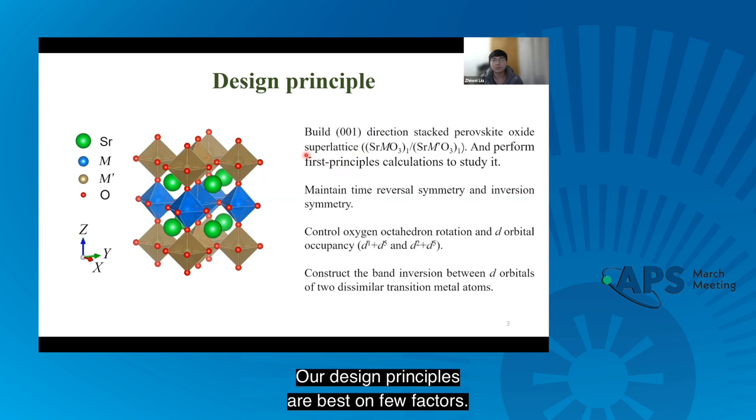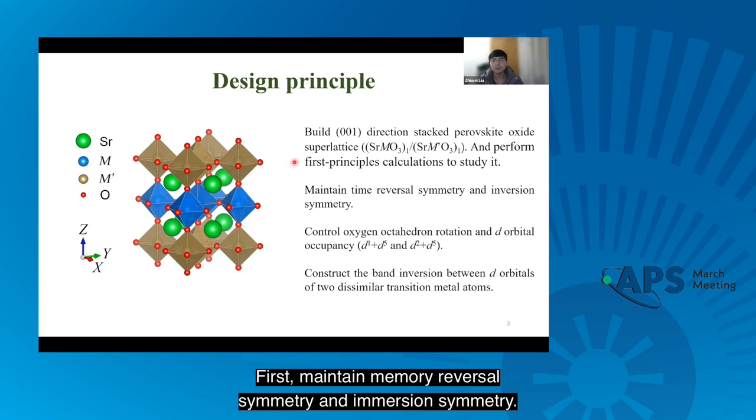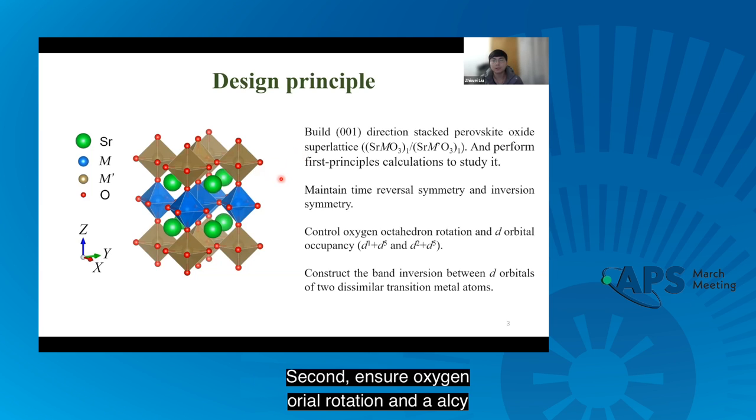Our design principles are based on a few factors. First, maintain time reversal symmetry and inversion symmetry. Second, control oxygen octahedron rotation and d-orbital occupancy. Third, construct the band inversion between d-orbitals of two dissimilar transition metal atoms.